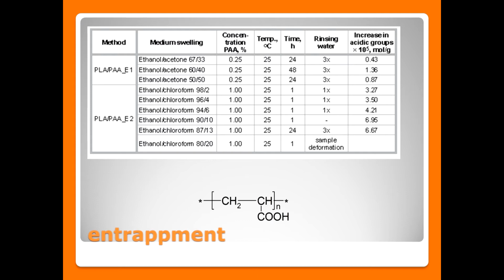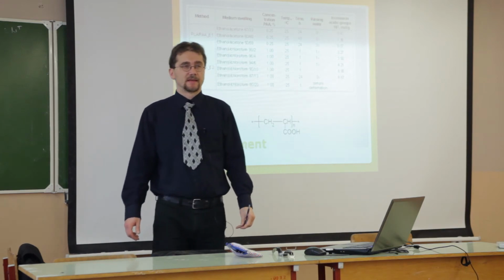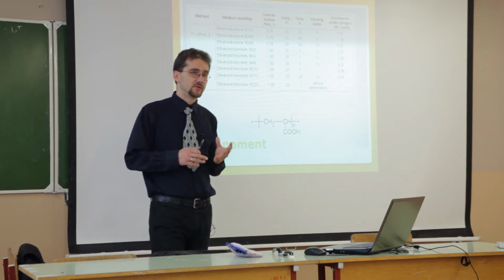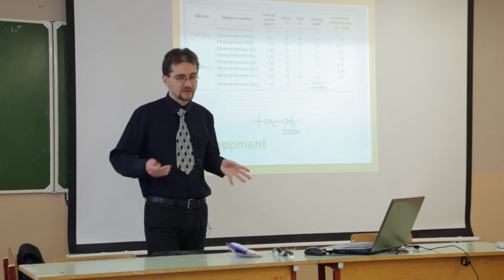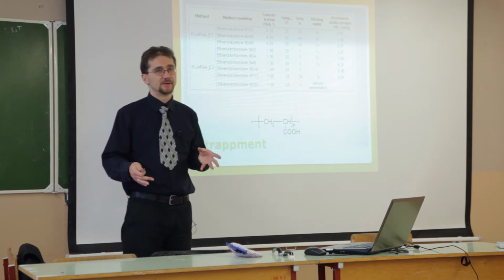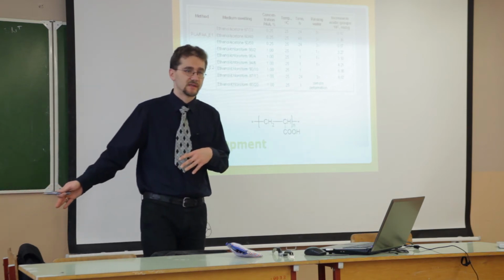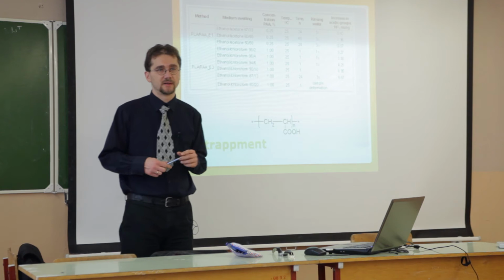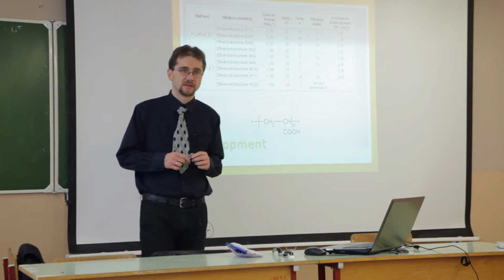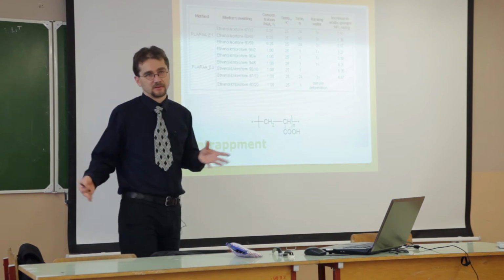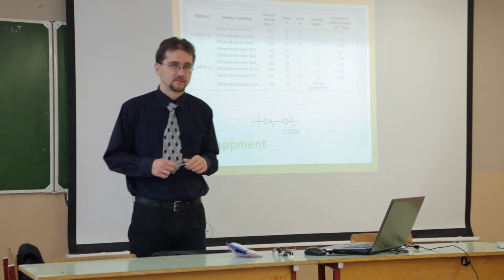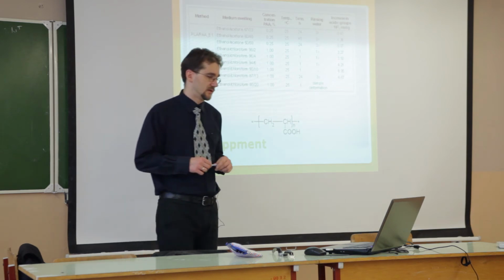This number depends on the process conditions. Sometimes it was a very long process, like 48 hours, but it was not necessary to use higher temperatures. So from an industrial point of view, it is sometimes easier to leave something for 2 days than to heat it for 2 hours at 80 degrees, because energy consumption by heating is very high. Leaving it for 2 days is not a huge problem for industry.